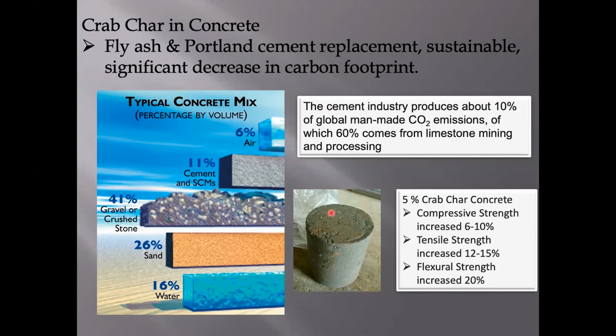project. And what we found was, with the addition of only 5% crab char to the concrete compared to the addition of nothing, just making the concrete using the regular recipe, we saw increases in compressive, tensile, and flexural strength. So that was a positive result. There was no negative impact anyways on the addition of the crab char.